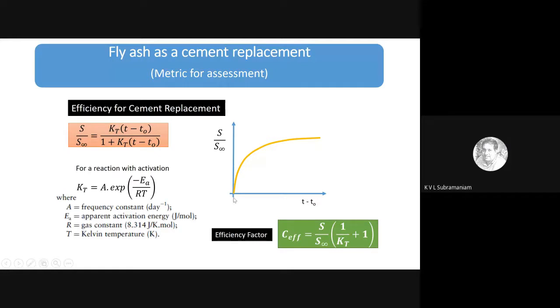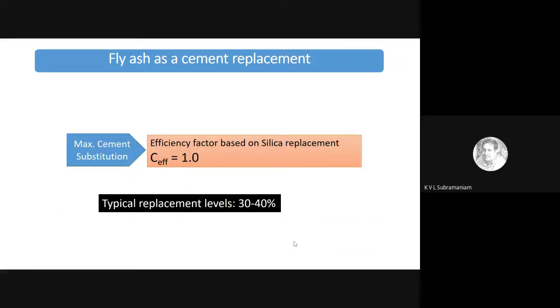So now with this efficiency factor that we've developed, the point would be to achieve an efficiency factor of 1. And if I achieve an efficiency factor of 1, then I have the optimal replacement level of this material, which is based on the reactive components that this particular fly ash is bringing into the system. So the maximum cement substitution with any of these post-industrial waste materials would be based on achieving an efficiency factor of 1, which would give me the same strength and performance as what I get using pure cement.